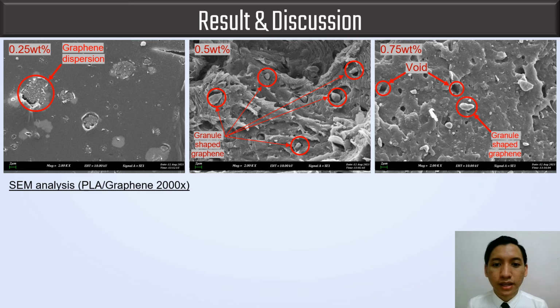Next, the SEM photos of the PLA blend with various amounts of graphene with the addition of Ultra Plus TP01, which acts as a compatibilizer. The compatibilizer has a fixed amount of 0.5 weight% for each composition, which is shown in the formula table earlier. We can see that the 0.25 weight% graphene blend shows the dispersion of graphene coated with the compatibilizer throughout the smooth surface of the PLA matrix.